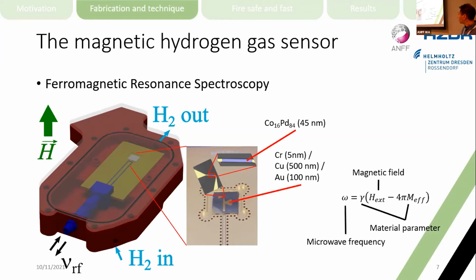It depends on the material parameter, which, for example, could be dependent on the cobalt content in our alloy, and on the magnetic field which we apply to magnetize the ferromagnet. Now, when this cobalt palladium alloy absorbs hydrogen, its material parameters change, and because we fix the microwave frequency, that means the resonance occurs at a different magnetic field. We supply the microwave energy to the cobalt palladium alloy using that waveguide shown there. That waveguide is a microwave microresonator. And I just want to acknowledge the people from the Helmholtz Center in Dresden-Rossendorf, because they came up with the idea. They fabricated this resonator, which is actually deposited on top of our cobalt palladium alloy.